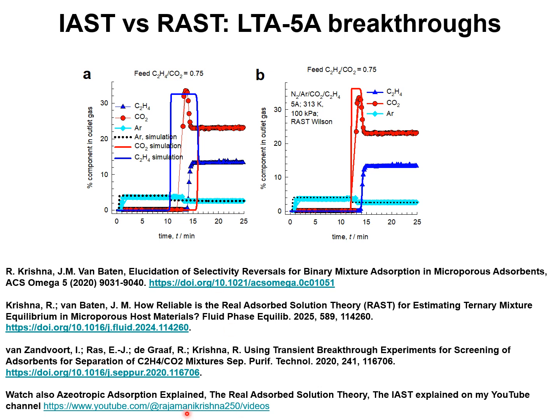I also explained this in my YouTube video, Azeotropic Adsorption Explained, that you can view on my YouTube channel. If we incorporate thermodynamic non-idealities and carry out breakthrough simulations using the real adsorbed solution theory with the fitted Wilson parameters, the breakthrough simulations shown by the continuous red lines and continuous blue lines are in good agreement with experimental data.